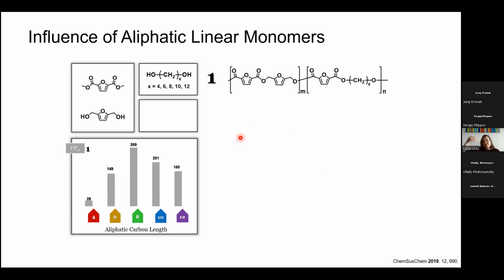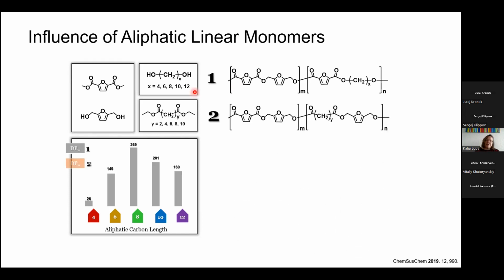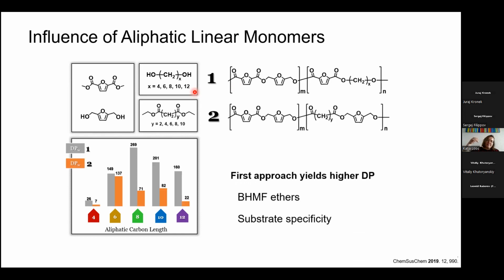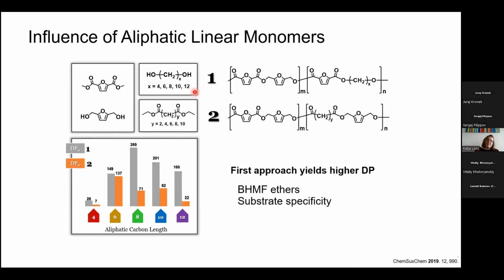So you first go with the acid group down, and if this is an FDCA and you release it with something flexible, that works quite well. So this is strategy 1. But if your acid group is first a flexible one and then you release it with something bulky, that's not so attractive for the enzyme. And that's why the first approach gives you the higher degrees of polymerization.